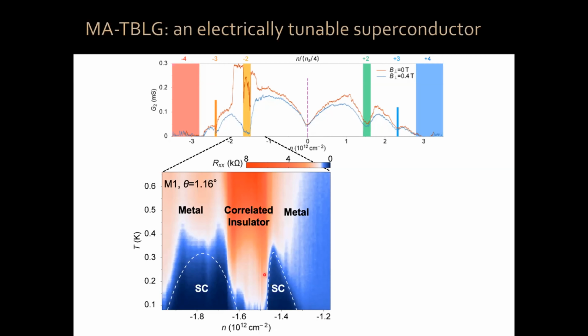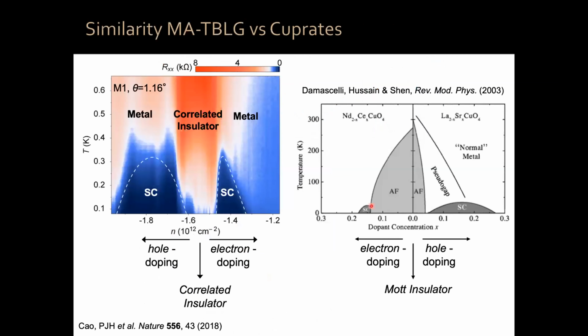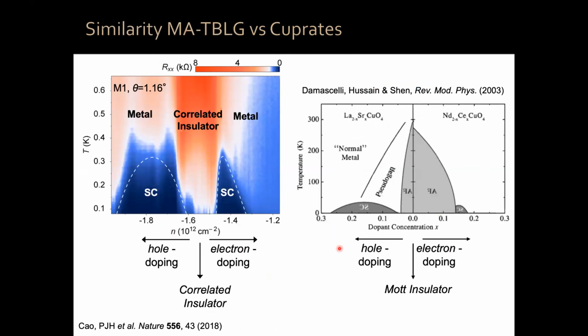So when my students showed me this, I was really surprised and fascinated, because this reminded me very much of the hundreds of times I had seen phase diagrams such as this. This is temperature and doping for the high temperature cuprate superconductor family. Now they get the doping in the wrong direction. Let me just flip it for you. Now it's correct. So 0 doping means 1 electron per copper site in the cuprates. It's a Mott insulator. If you dope with holes, you have a big superconducting dome. If you dope with electrons, you have a small superconducting dome.